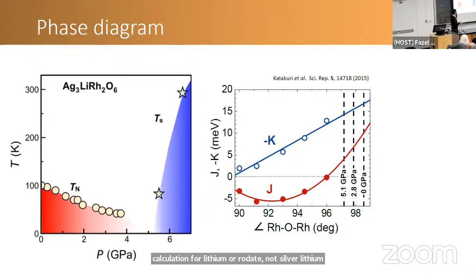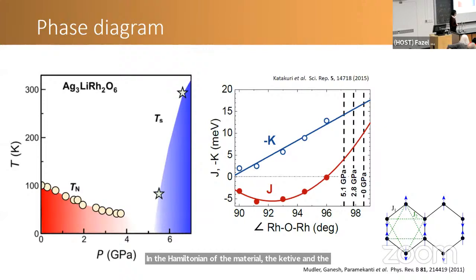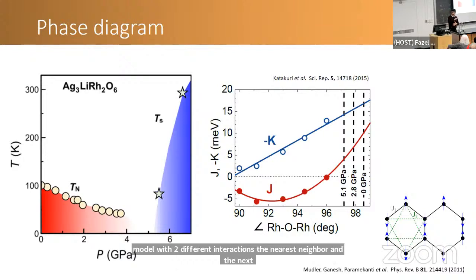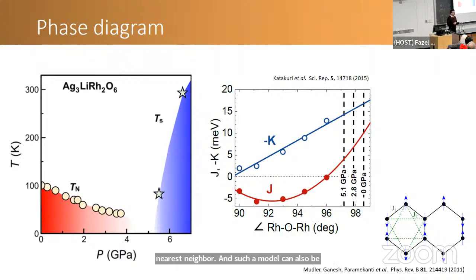And so we basically demonstrate that probably what we're doing with pressure is to tune the relative strength of these terms in the Hamiltonian of the material, the Kitaev and the Heisenberg term. There could be another interpretation of this physics. Again, going back to my years as a PhD student, Professor Paramekanti and his student Ganesh have been working on J1, J2, or more recently J1, J3 models of competing interactions on a honeycomb lattice. And this model is also a frustrated model with two different interactions, the nearest neighbor and the next nearest neighbor. And such a model can also be frustrated as long as J2 is antiferromagnetic. If I understand correctly, there is frustration in this model.